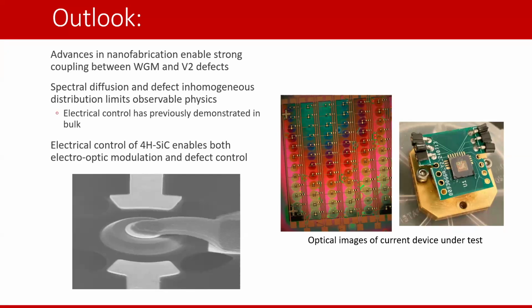So this is evident that even out here, and it's actually probably this one, not the one out here, it's really the one in the center that's impacting the optical modes there. But this is actually another reason to be careful with PIN doping, because those doped regions will kill your optical mode as well. Photonics needs to be in the intrinsic layer. Exactly. Yeah, no electrodes.